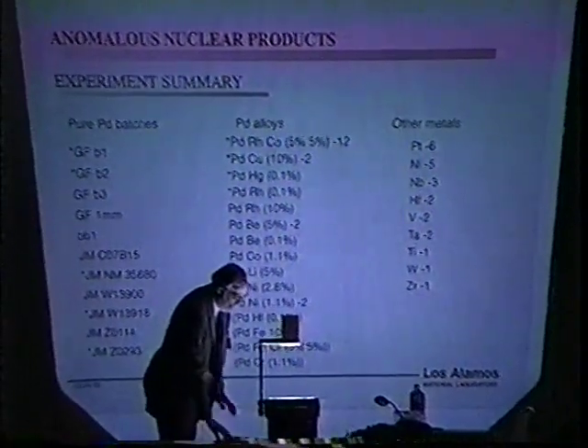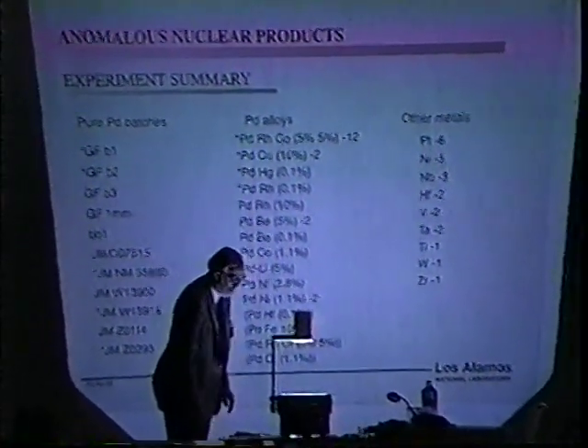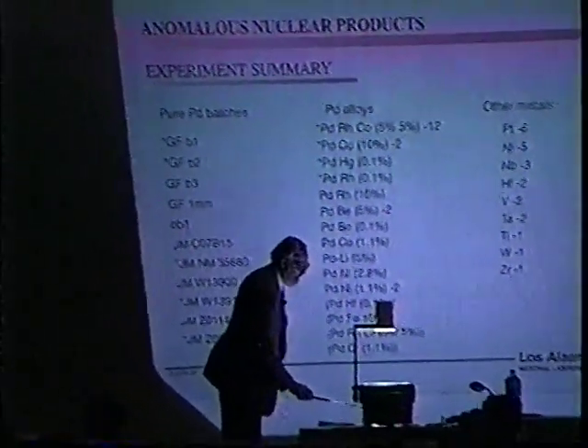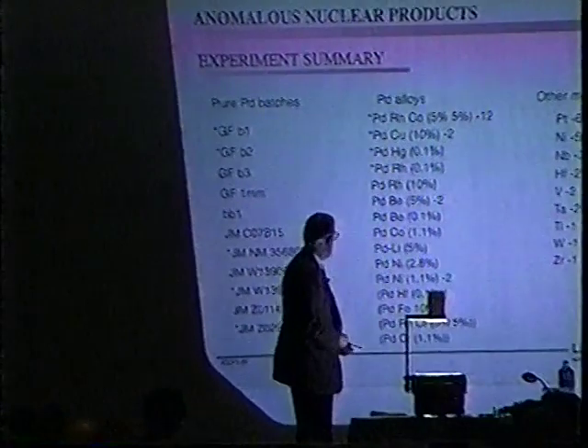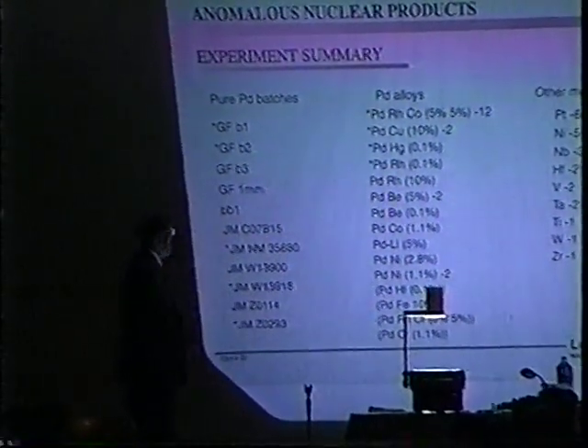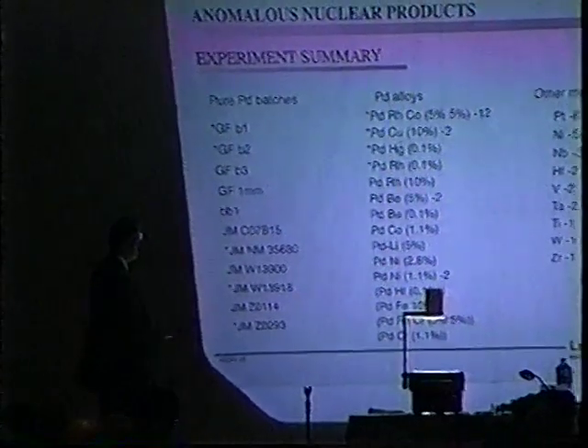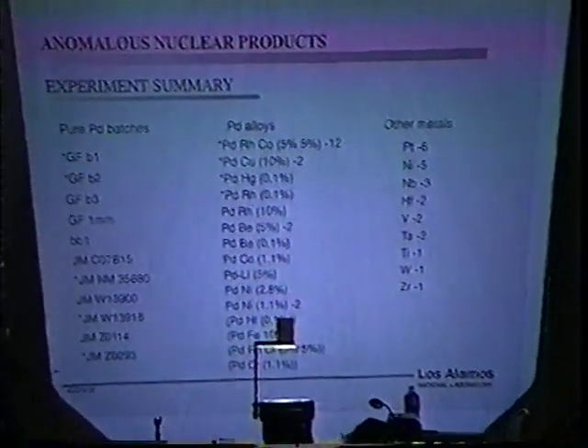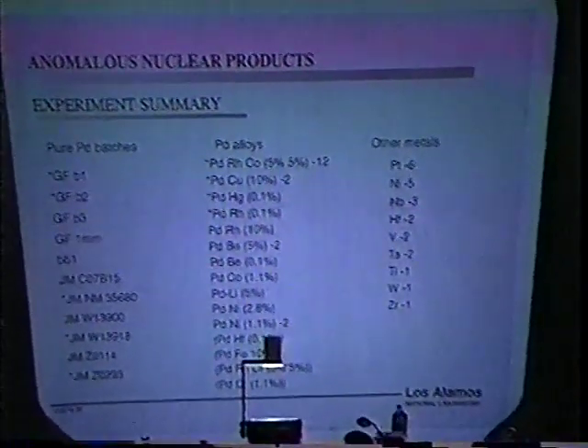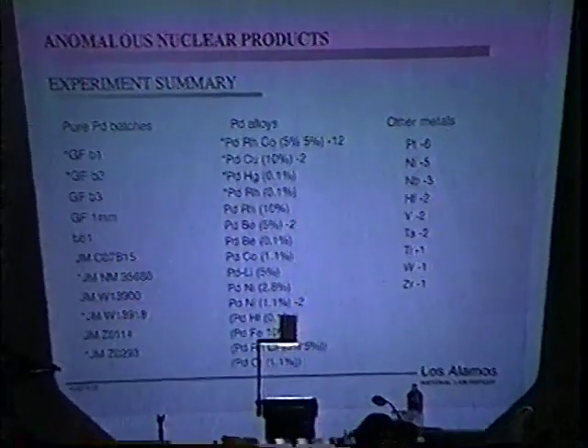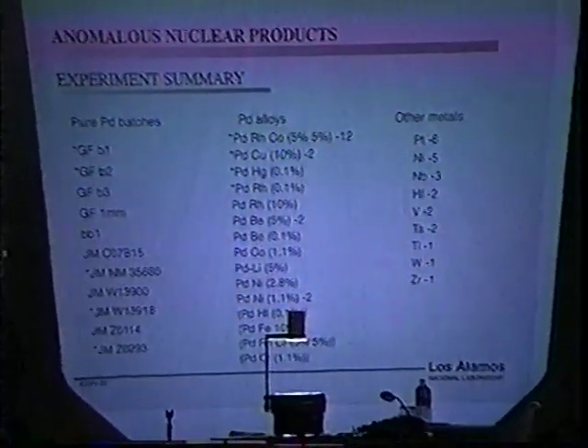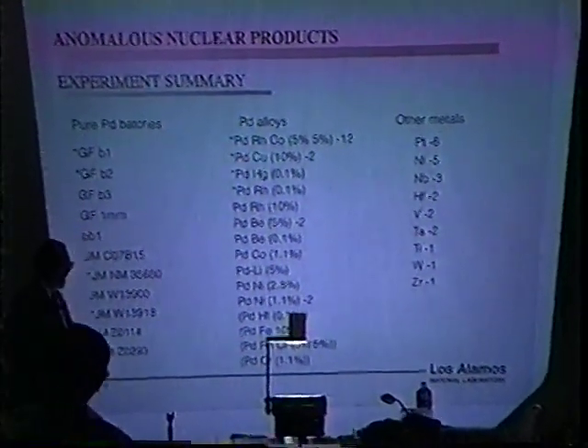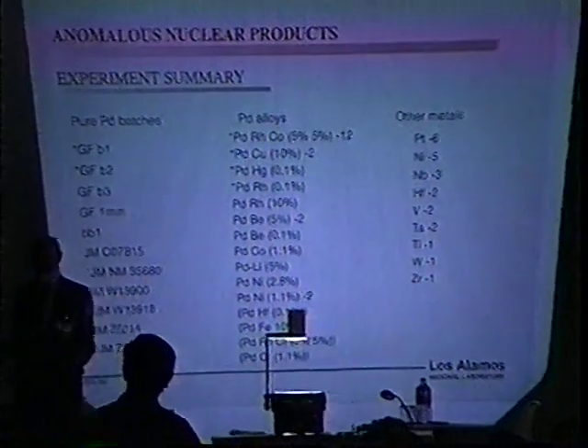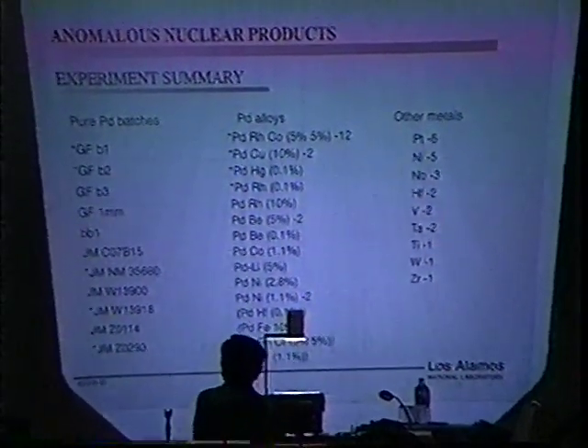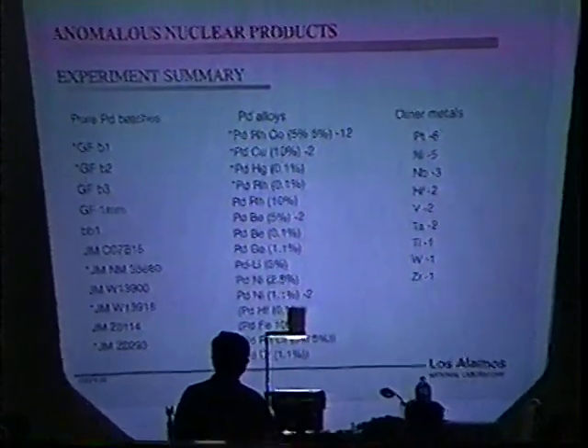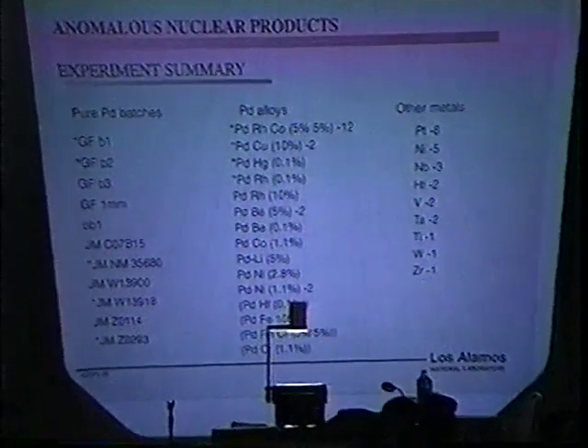Tom started by looking for tritium in various pure samples of palladium. These are listed here in the first column. The samples that show an asterisk are ones that gave excess tritium. And the first one, the good fellow B1, was the all-time favorite, giving between 1/10 and 2/10 nanocuries per hour of tritium, quite reproducibly. Unfortunately, they ran out of the stuff, and it's been somewhat of a problem repeating that.